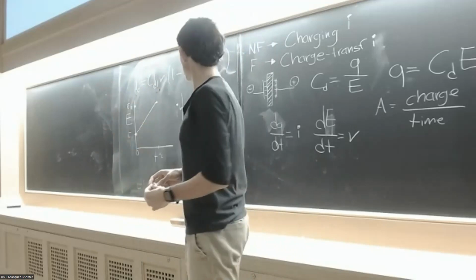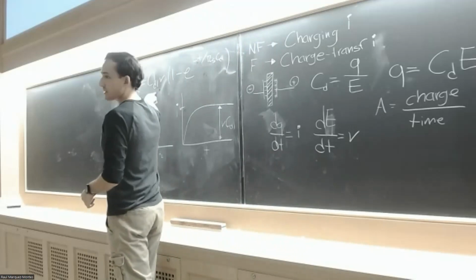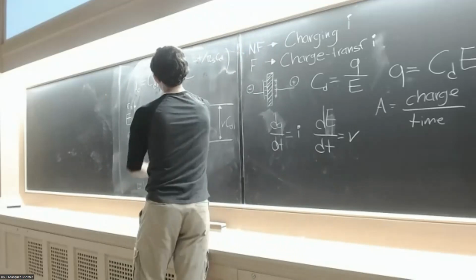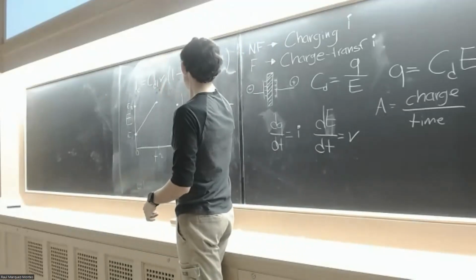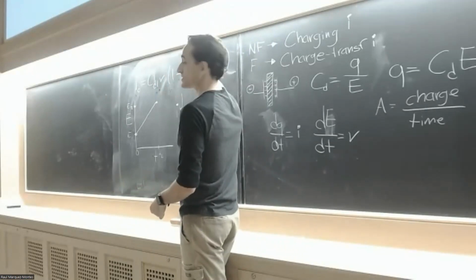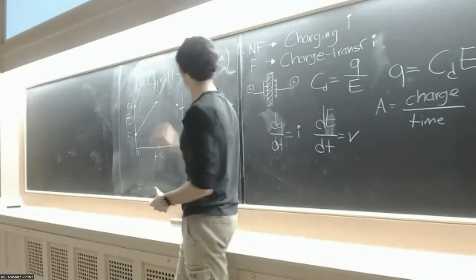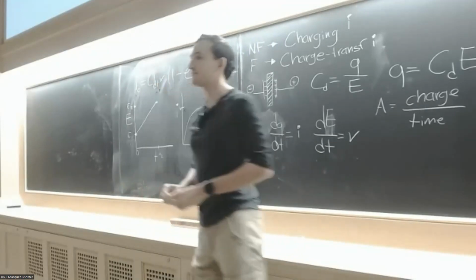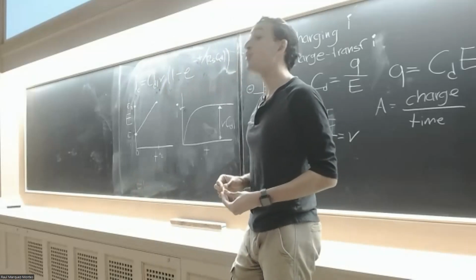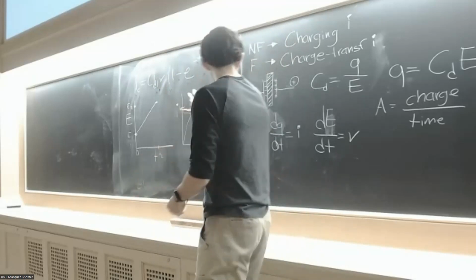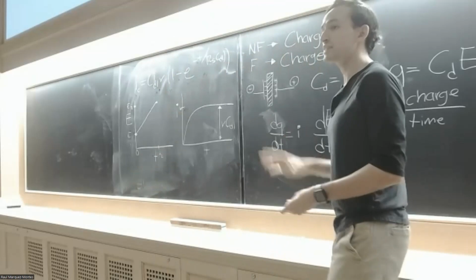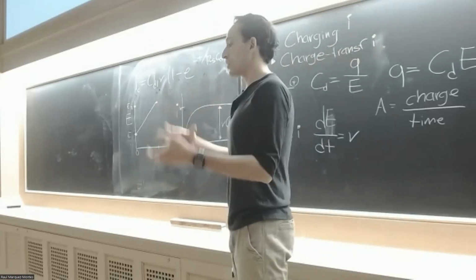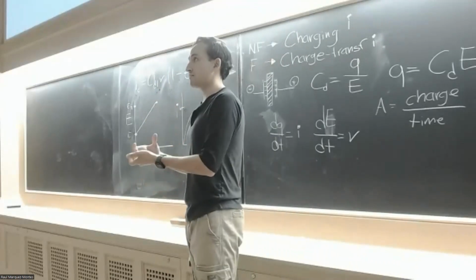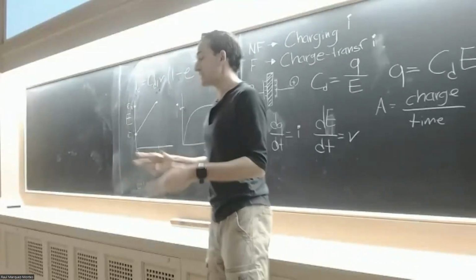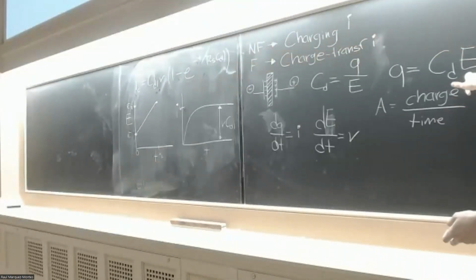How did you write the equation on top? IC equals double layer capacitance times the scan rate and times this term. So this term is 1 minus e to the minus t over the time constant, resistance RS times double layer capacitance, and this is divided by this term. My question was how did you arrive at that? Oh, how do I get to that one? You need to solve this differential equation. You need to take into account all the potential contributions. The potential is caused by the potential that you apply and the ohmic drop due to the resistance. So you need to take all that into account in this equation, and then input these differential terms here and solve for I.